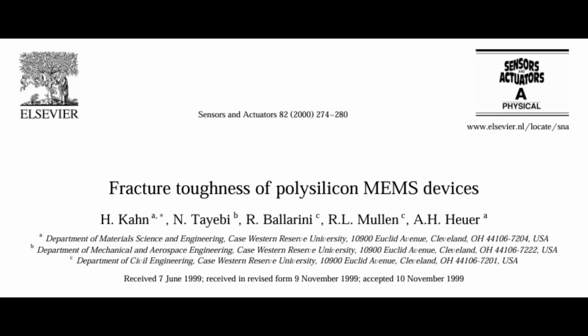They did. Some tried using micro-machined notches, sort of pre-cutting a tiny weak spot to encourage a crack to start there. Okay, makes sense. But the issue is, these tiny etched notches, they aren't perfectly sharp like a natural crack. They have a slight radius, a curve, at the tip. Ah, not a true sharp point. Right. And the calculations engineers use to predict fracture, these stress intensity factors, they assume a perfectly sharp crack tip, a singularity. So using these rounded notches, it introduces errors. It's like trying to measure precisely with a ruler that's a bit bent. Gotcha. So the measurements weren't quite reflecting the true material property.